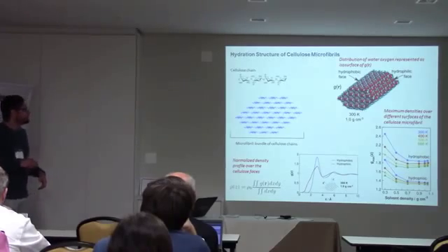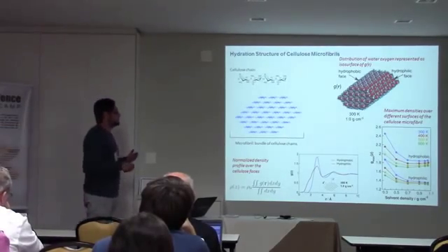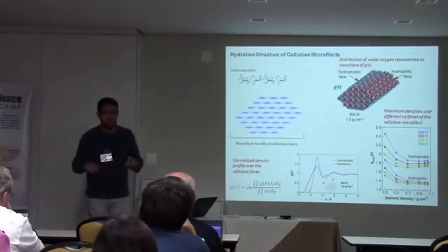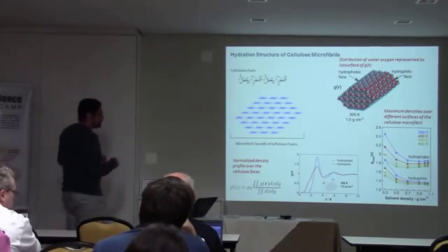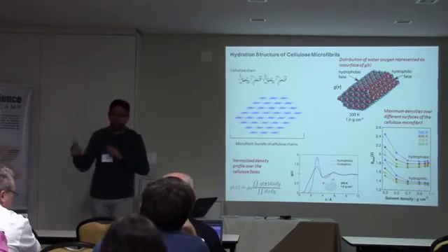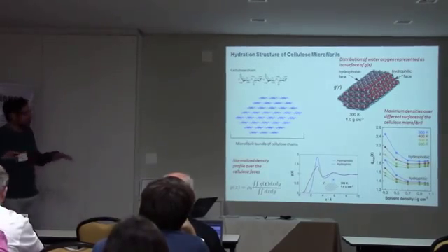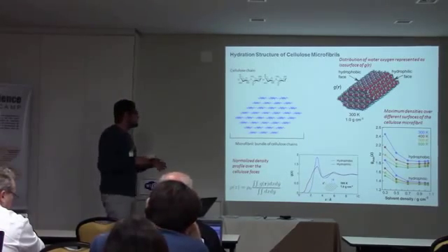This is the kind of data that we get from the theory. You can see that it's quite heterogeneous, because the cellulose surface has lots of different chemical groups exposed, so we have different specificities. So water is not distributed homogeneously over the surface.